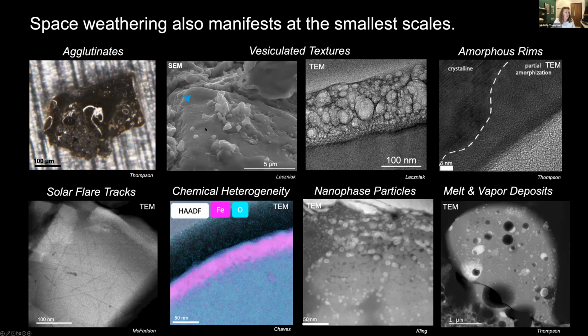There's a scale bar there. If you look closely, there's this sort of hummocky texture, or bubbles or blisters, spread out across the surface. These are the product of implanted solar wind hydrogen and helium that's accumulated into these bubble textures.